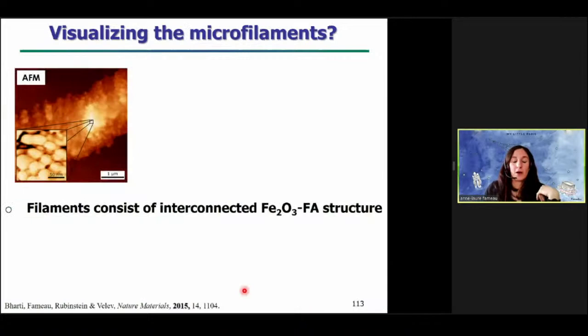Then, to understand the structure of these filaments, we use different types of microscopy experiments. First we use atomic force microscopy experiments. And as you can see here, the filaments are very thick, because the thickness is around 50 to 100 times thicker than just one single nanoparticle. And the particles are embedded in a quite thick shell of fatty acids.